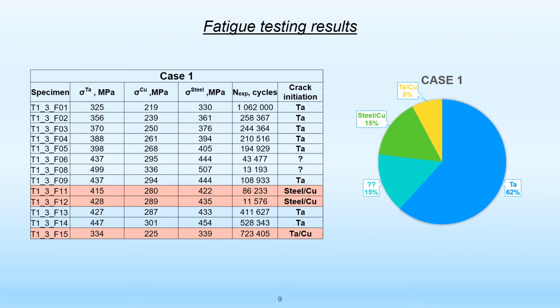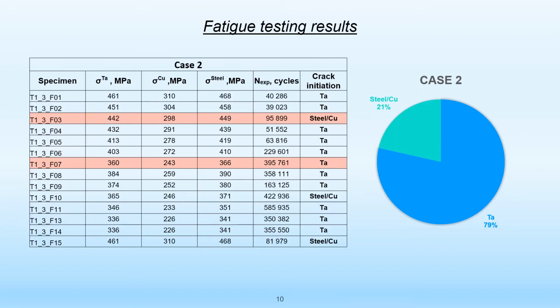For the values of stress amplitude in tantalum under 415 MPa, all the primary cracks were identified in the tantalum layer. For the values of stress amplitude in tantalum over 415 MPa, primary cracks were observed at the interface of steel and copper layers or were not possible to be spotted due to major plastic deformation. A similar behavior was observed for case 2 at a higher stress level of 461 MPa, with the exception of one specimen which failed from steel and copper interface at a lower stress level. Almost 80% of the specimens failed in tantalum layer. Only 3 specimens failed due to crack originating in steel-copper interface.